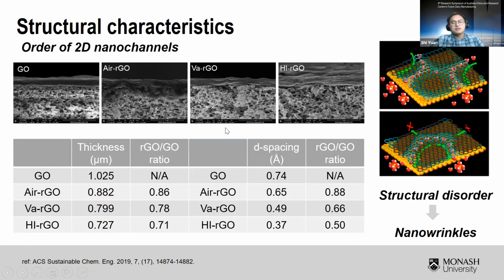So we then double checked the order of the 2D nanochannels, as mentioned by Yang before. The order of the channel is a key factor when we consider the rejection of small ions. So we analyzed the RGO to GO ratio in thickness and in interspacing. If these two ratios match well with each other, it means the membrane is uniform. The table shows that only Air-rGO has similar ratios in both thickness and interspacing. While for the other two reduced GO membranes, the structure is quite disordered.